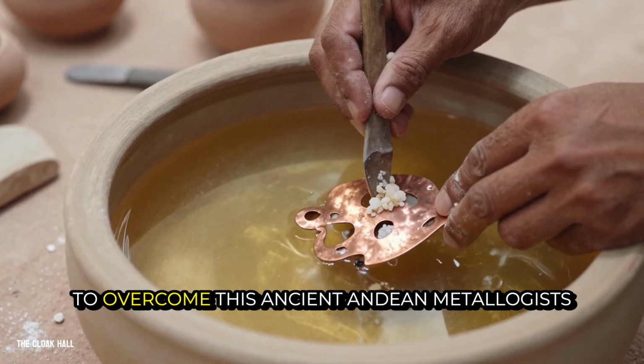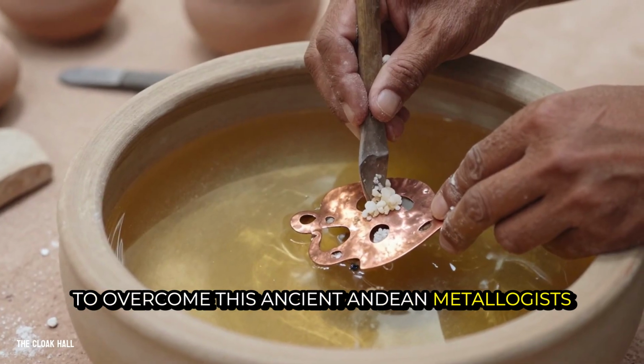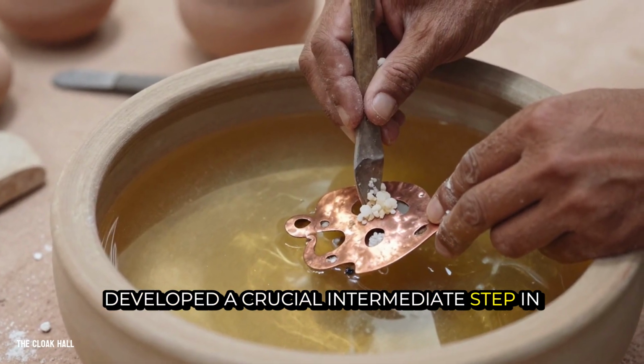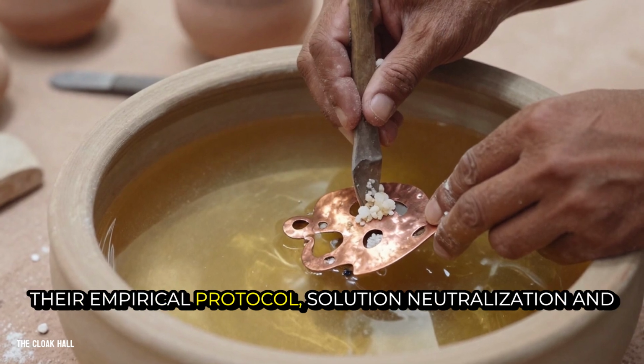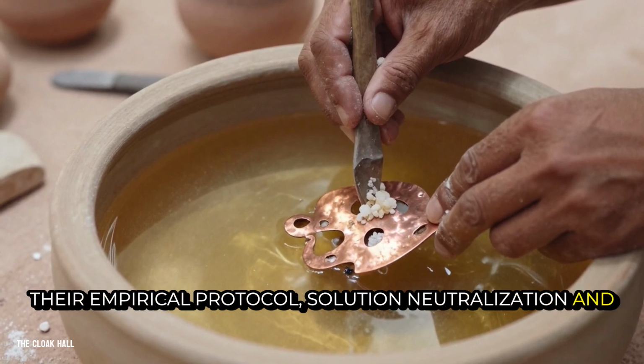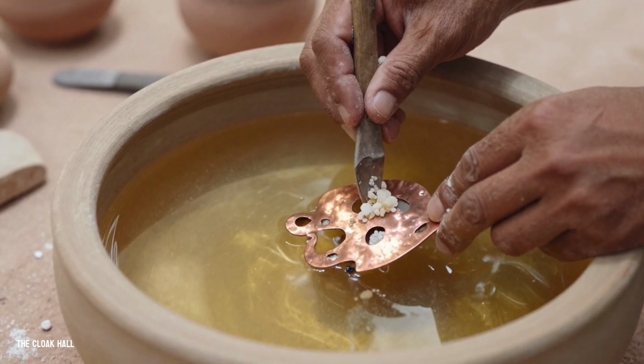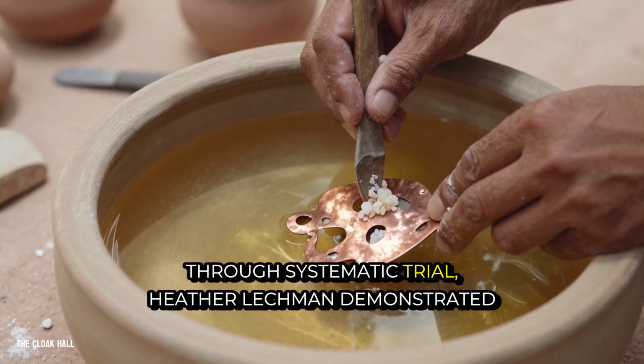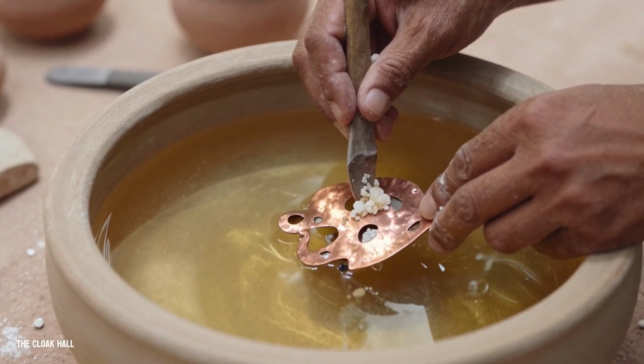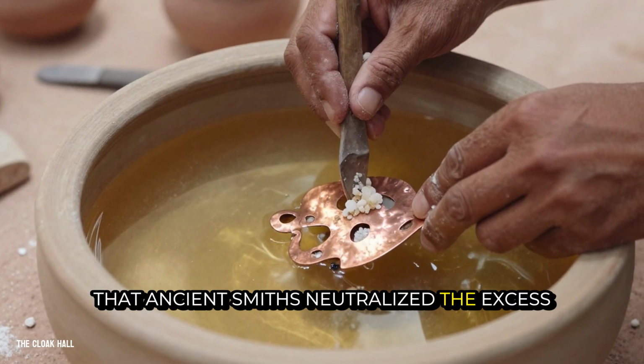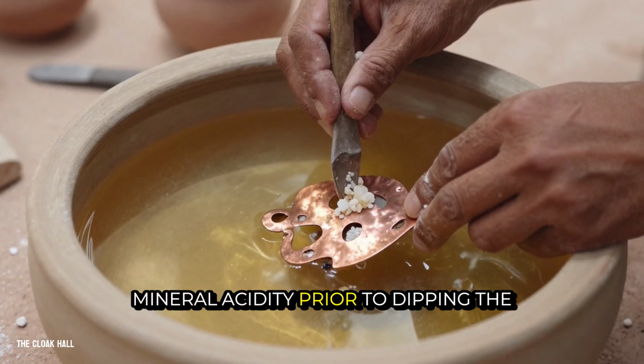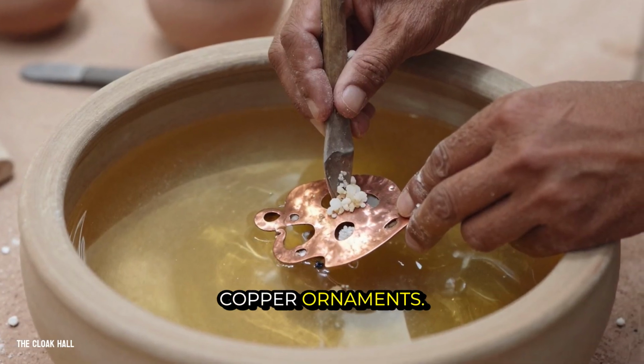To overcome this, ancient Andean metallurgists developed a crucial intermediate step in their empirical protocol: solution neutralization and chemical buffering. Through systematic trial, Heather Lechtman demonstrated that ancient smiths neutralized the excess mineral acidity prior to dipping the copper ornaments.